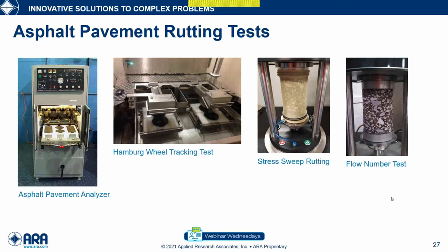Here are some tests that are typically done for rutting. These are some of the more common tests. You have the asphalt pavement analyzer, the Hamburg wheel track test, the stress sweep rutting test, and a flow number test. Again, some of these are simple index tests. For example, the stress sweep rutting test might give you more than just an index property. It will give you something that would allow you to even model the performance of the material. So there are different types of tests that give different properties.